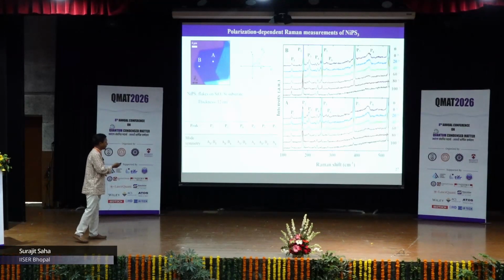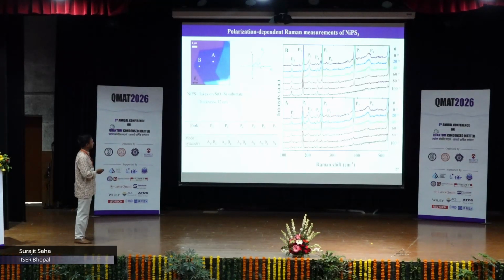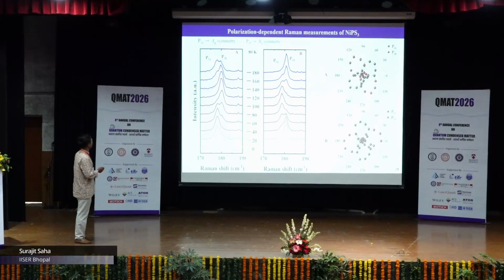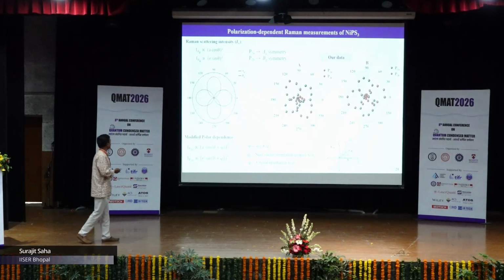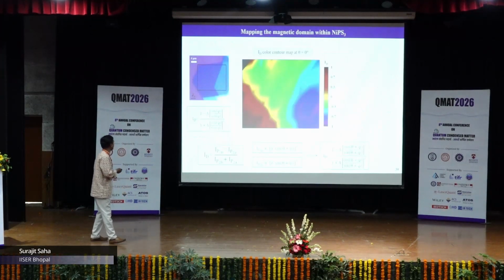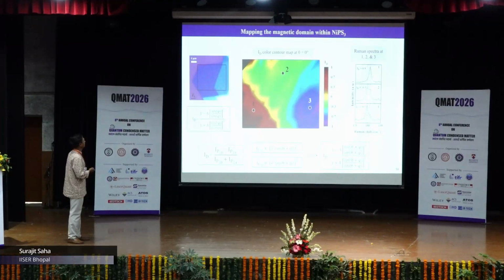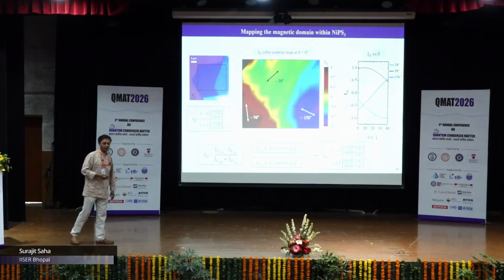Of course, there's a mapping, and these are the various Raman spectra, and then we carefully analyzed the data. What we can see is that these two modes show these lobes, and these lobes would basically orient depending on the spin orientation. Here you can see the three different orientations. This is one orientation of the spin, this is another orientation of the spin, this is the third orientation of the spin for the same flake.